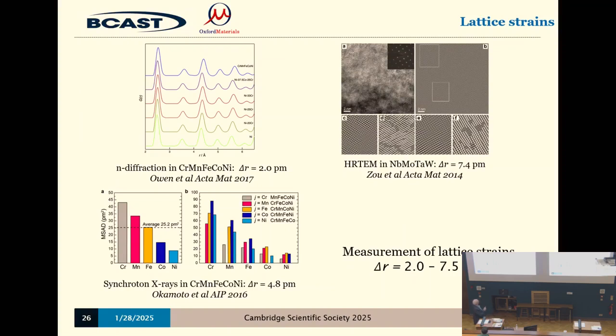Neutron diffraction says about 2 picometers. Synchrotron X-ray says about 5 picometers, about 2% and about 5%. In the body center cubic materials, it's a little bit higher. It goes up to 7%. These are big strains in the material. So there's this landscape of varying strains going over enormous distances in these materials, and that's what gives lots of